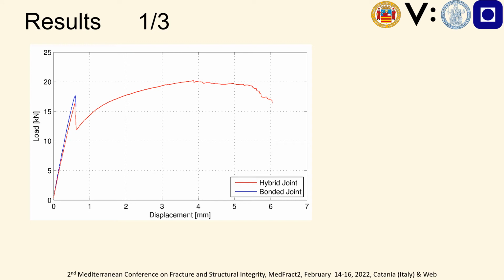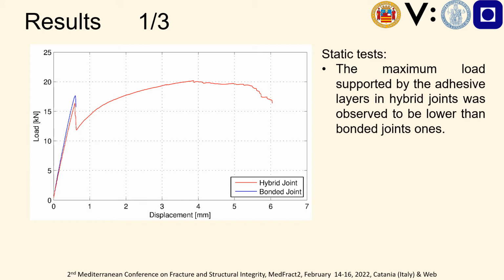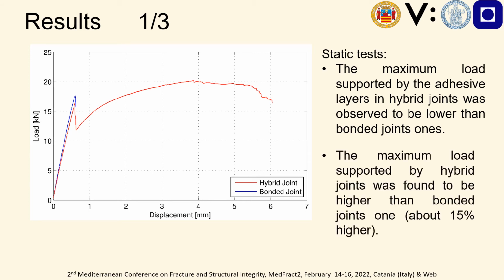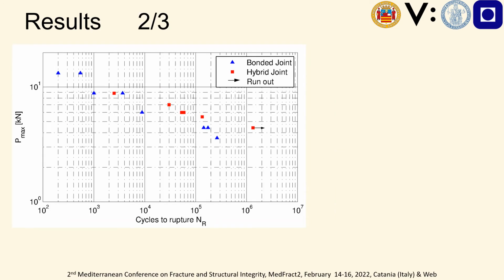Concerning the results, you can find here the load versus displacement curve for both hybrid and bonded joints, and in particular, according to this picture, we can find that the maximum load supported by the adhesive layer in hybrid joint is lower than the one supported in the bonded joint. Moreover, we can observe that the maximum load supported by hybrid joint is higher than the one supported by the bonded joint by about 15%.